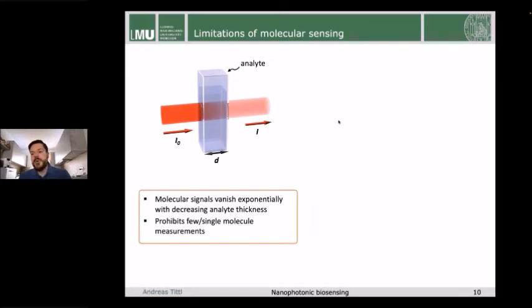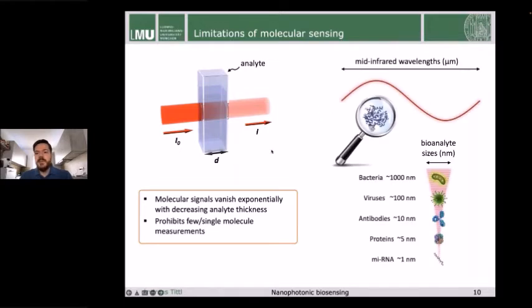Now, there are, however, some important limitations of infrared spectroscopy. In general, if you think about light passing through some sample, the molecular signal vanishes exponentially with decreasing analyte thickness. So if you make the sample very thin, you will get less and less signal, and it will be difficult to separate the signal from the background. This truly prohibits single molecule measurements and makes it very challenging to investigate the relevant biomolecules in many biological systems. The physical reason for this is that the mid-infrared wavelengths are on the order of microns, whereas relevant bioanalyte molecules can be as small as 10 or 5 or even 1 nanometer. So we have a 2 to 3 order of magnitude difference in the length scale, and the absorption cross-section is very low.